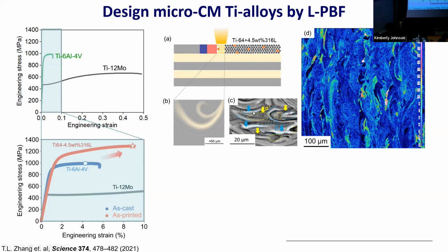Upon cooling, you can see structurally that you have a very fine scale dual phase. One is the alpha prime martensite in those regions, and in those other regions you have the metastable beta phase. And the beta phase is not uniform either. It's a metastable beta, and you have a gradient of the metastability. You're going to transform into martensite at different stress levels. That's back to the same idea I presented for the shape memory alloys.